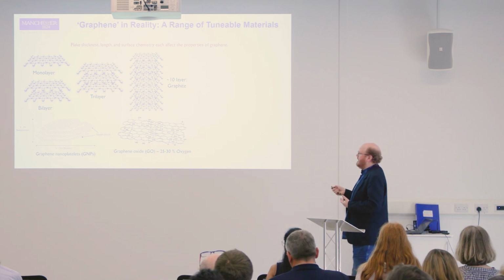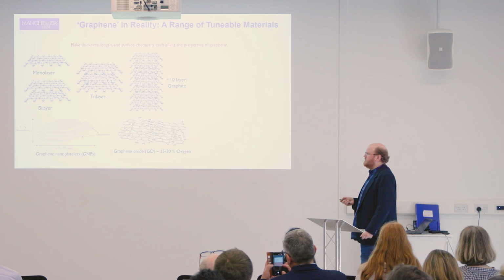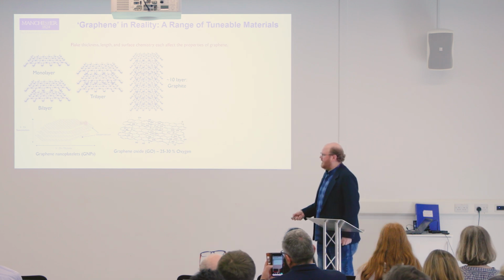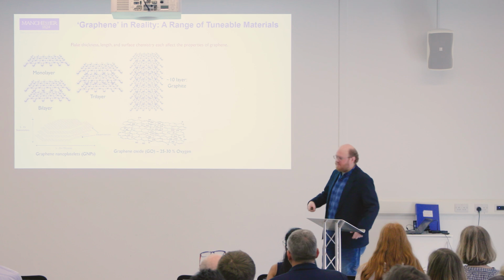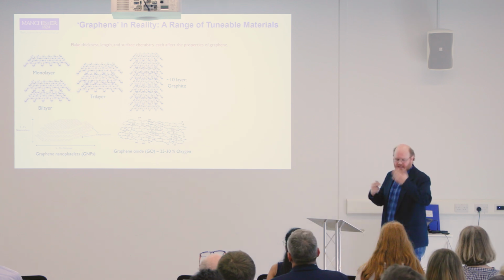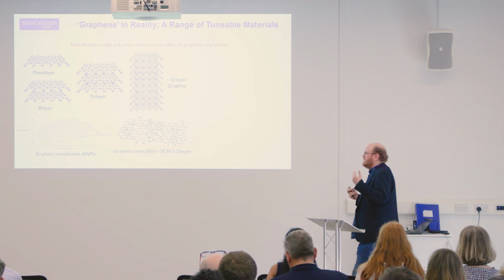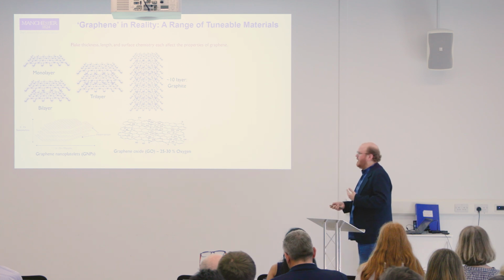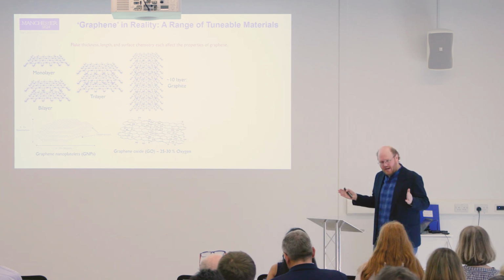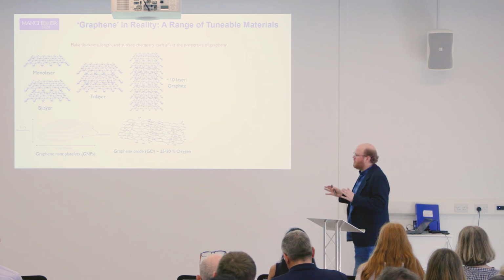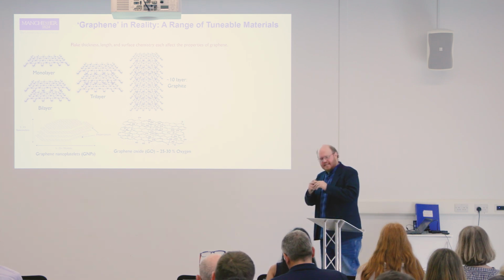And then of course you can stack these together, and then you've got graphite, which is of course the base material. But then you've got a subset of materials like these graphene nanoplatelets, which might be tens of nanometers thick. So that's clearly much more than 10 layers. So it's essentially graphite, but it's very large lateral size. So it might be on the order of 20 odd microns, but only a few nanometers thick. So its very high aspect ratio is really what makes it behave differently than, say, bulk graphite. Even though technically it's not graphene because it's many layers thick, its behavior is very different. So that's why it's a subsection of these materials.